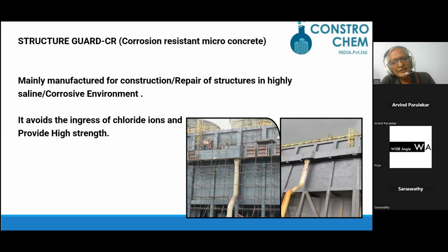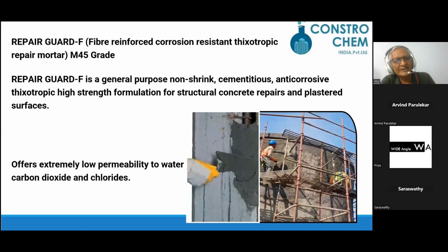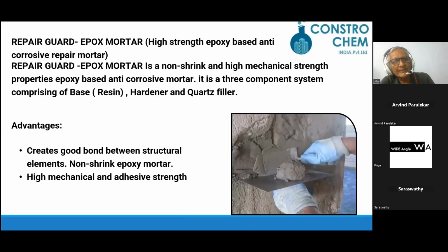It avoids the ingress of chloride ions and provides high strength. Repair guard F, fiber reinforced corrosion resistant thixotropic repair mortar. Repair guard F is a general purpose, non-sag, thixotropic, high strength formulation for structural concrete repair. It offers extremely low permeability to water, carbon dioxide and chloride. Repair guard epoxy mortar is a non-shrink, high mechanical strength, epoxy-based anti-corrosive mortar.